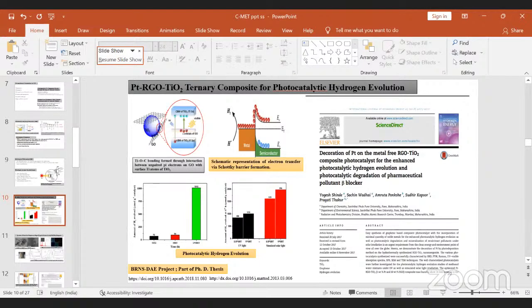Okay, so we need to see some other strategies or remedies which would decrease the percentage of platinum in the system, because till now the highest efficiency shown by the platinum TiO2 system, which is supposed to be the base system, is 22.6% quantum efficiency, with a platinum percent of 2.5% in the platinum TiO2 composite. Okay, so 2.5% is a very high percent. So we focused our research on whether we can decrease this platinum percent by some strategy.